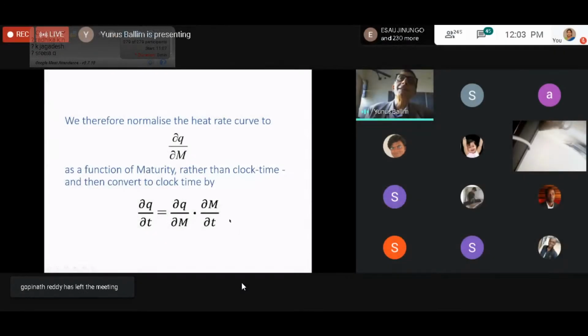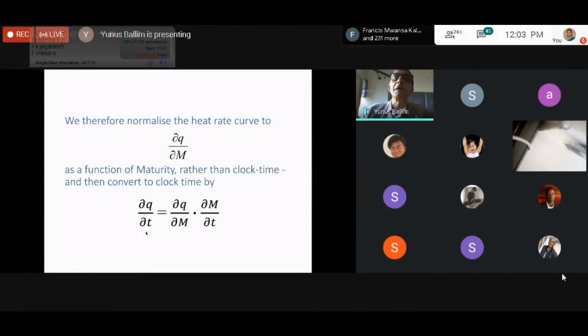And you can see here, I'm sorry I'm going through a very complex discussion in a fairly short period, but what we're effectively doing here is accounting for the time temperature history. And that then brings us to dq by dt, which accounts for time temperature history. It may sound a little bit abstract, but I'm going to show you that it actually works.